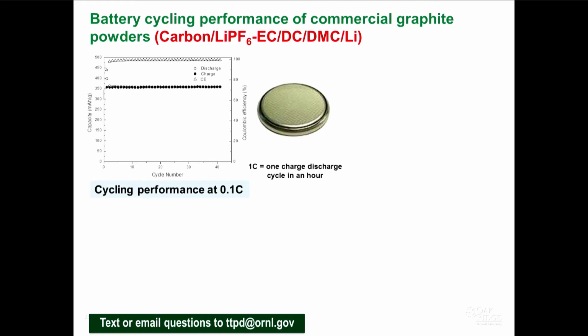I have plotted the cycling performance of these batteries, the commercial graphite, at 0.1C, one-tenth of a charge discharge. You can see the plot: on the right side is the Coulombic efficiency, and at the bottom both charge and discharge, and the capacities are close to 350 to 360 milliamp hour per gram. After 2 cycles, the capacity comes down because of the reaction between the anode and the electrolyte, the solid electrolyte interface. So you do see a small drop. Then it's pretty constant over the 40 cycles we have shown.